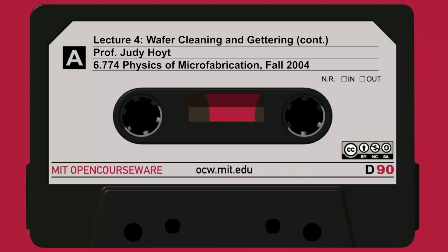And zinc comes down uniformly. Look at the amount of zinc that's introduced by the CMP process that is not removed by sulfuric acid. It's not until it goes through the RCA Clean that you get that down below the background. So the RCA Clean can be very effective in removing contaminants, even ones that come from a very dirty process, which is basically like a sandpaper type of process, almost, the CMP slurry. So it's certainly required.